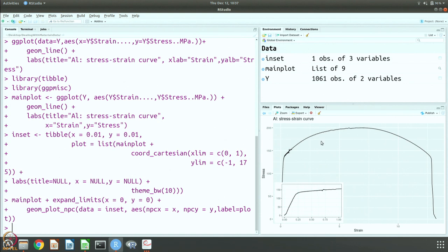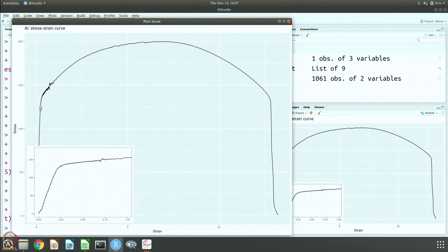As you can see, there is this main curve, and we have taken a small portion from here and expanded it. If you zoom in, what looks like a neat straight line here actually has lots of wiggles. So what we need is a smooth curve. You can also see that the initial portion still has some problems, because maybe the stress strain measurements are not really perfect here. This looks like a straight line, and if you extend it slightly it should go something like this, but it has a different slope. This is a common problem initially when you put the sample in, put the grips on and try to do the experiment. Maybe there are small adjustments that have to take place before proper loading happens and your measurements of load and displacement are reliable.